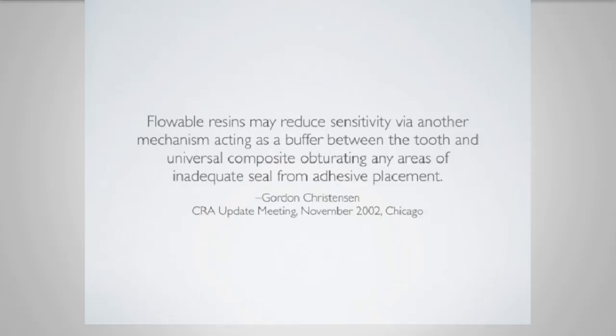And in pooling studies, some studies have shown decreased microleakage when flowable composites are used as a liner at the gingival margin. Others have discouraged the practice. Some research has concluded the location of the gingival margin, either above or below the cemento-enamel junction, is the most important factor in determining the best restorative material to use. In these studies, glass ionomer cement has been suggested over flowable composite because of its adhesion properties and lack of shrinkage, to prevent microleakage in areas that are below the cemento-enamel junction. So different techniques as far as filling these restorations. When you pull together the results of these studies, it appears that the use of flowable composite as a liner in the proximal box is recommended to increase cavity adaptation and reduce microleakage. So that's what I'm going with.